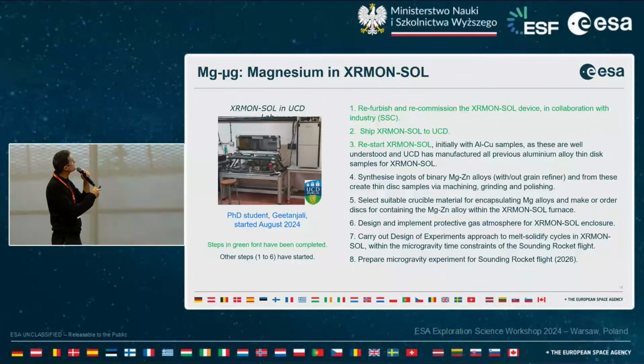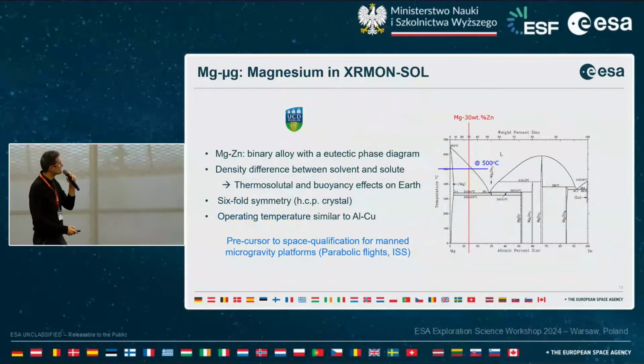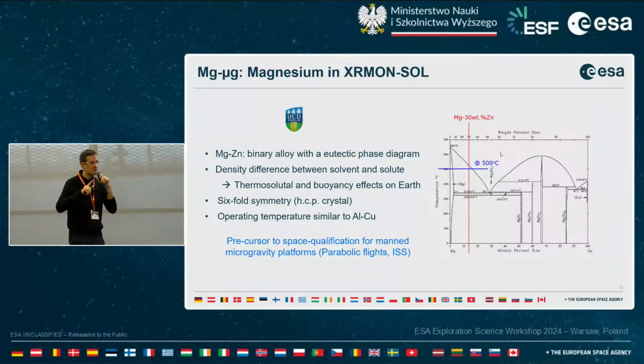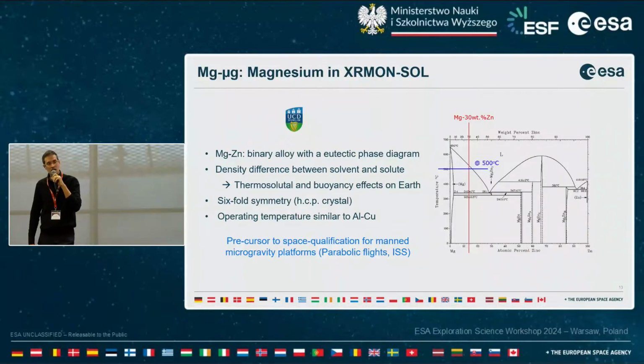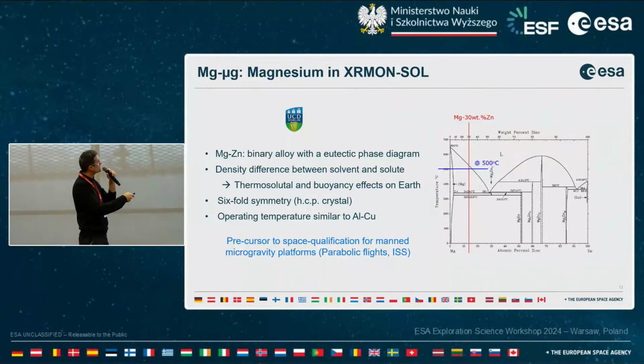But it will be interesting to study another base material, that is magnesium. I did not mention it, but one of the main differences is that it has a six-fold symmetry. It's a hexagonal close-packed crystal compared to aluminum, which is a cubic crystal. So we expect the dendrite tip kinetics to be different. It will be quite interesting to study the dendrite kinetics for a six-fold symmetry.